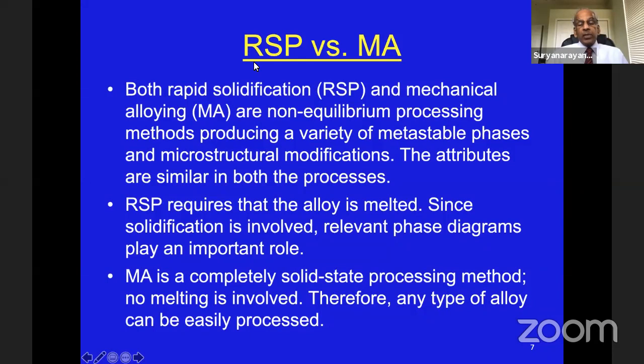Now, another technique which was very popular around the same time was called RSP. It's called Rapid Solidification Processing, RSP, and mechanical alloying and RSP, both of them are non-equilibrium processing methods. That means by subjecting the materials to rapid solidification processing or mechanical alloying, you produce a variety of metastable phases, and you can change the microstructural conditions. That means instead of crystalline, you can make it amorphous, you can make it nanocrystalline, you can make it quasi-crystalline, or many other possibilities of combinations exist. And therefore, the attributes of both RSP and MA are very similar.